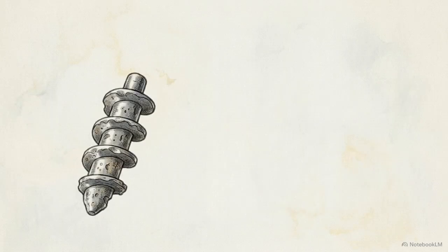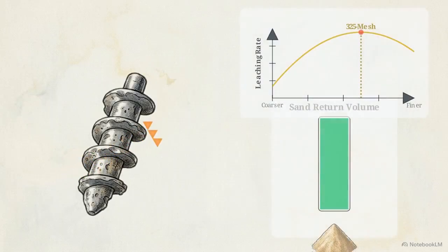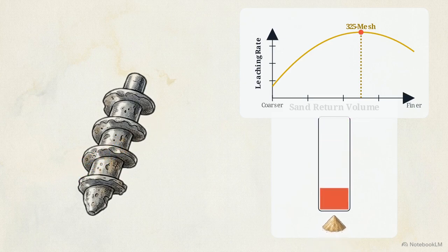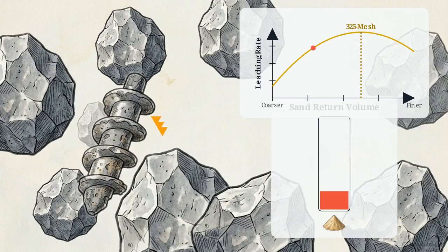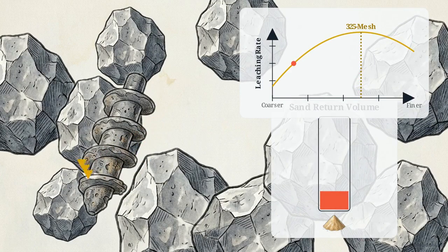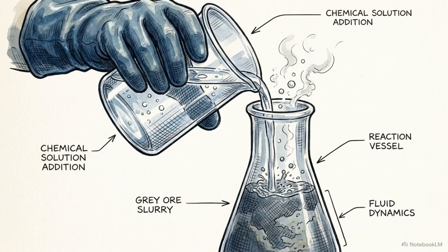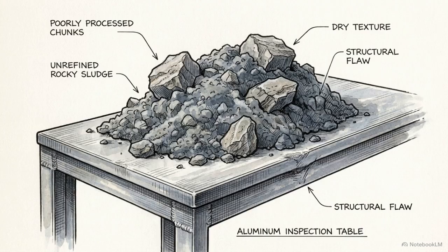As these blades wear down, they are less effective at moving material, which reduces the volume of returned sand within the classifier. This drop in sand return causes the overall grind to become coarser, pushing the material away from our 325 mesh recovery target. Even if your chemical mix is perfect, failing to maintain these mechanical components leads to a coarser product that inhibits the extraction process.